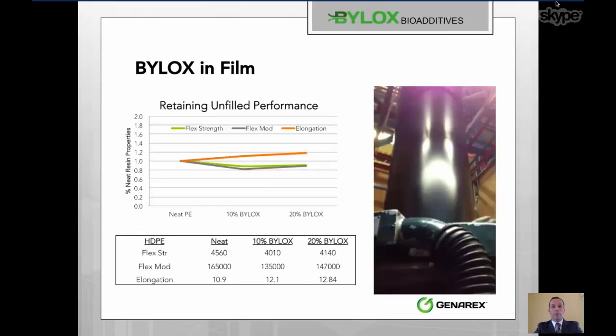So Bylox in film, this is one of the application spaces that we're very excited about. For HDPE as an example, we do not add stiffness like you would typically see, but we act as a very effective resin extender. Here you'll see in this chart 10 and 20% loaded Bylox in films that ran very smoothly. We can get down into finer and finer film thicknesses depending on what the customer's needs are, and we continue to push that envelope every day.